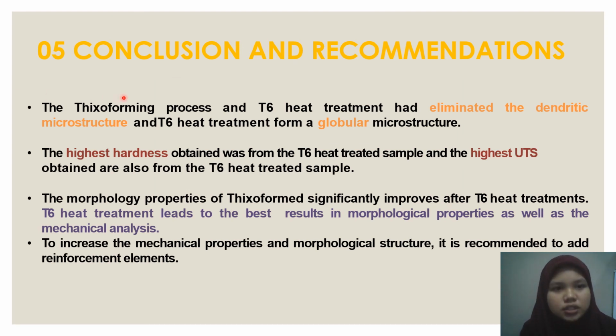As a conclusion, the THIXOFORMED process and T6 heat treatment had eliminated the dendritic microstructure, and T6 heat treatment formed a globular microstructure. Secondly, the highest hardness obtained was from the T6 heat treated sample, and the highest ultimate tensile strength obtained is also from the T6 heat treated sample. Thirdly, the morphology properties of THIXOFORMED significantly improve after T6 heat treatment, and T6 heat treatment leads to the best results in morphological properties as well as the mechanical analysis.